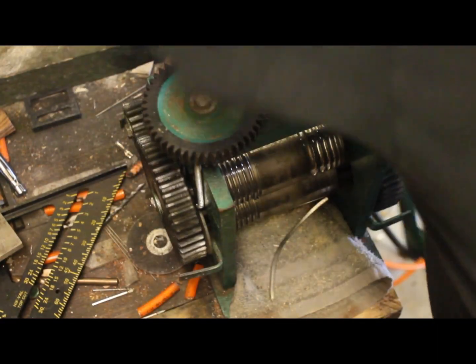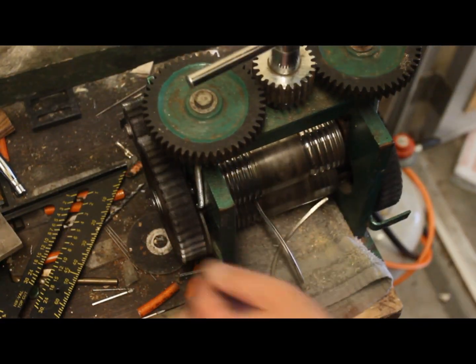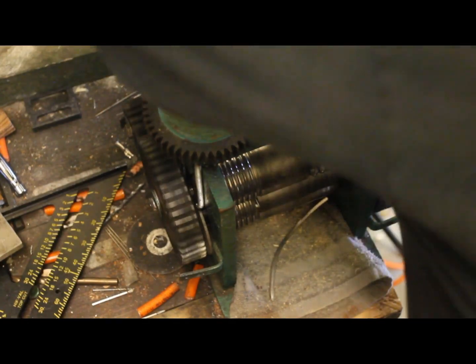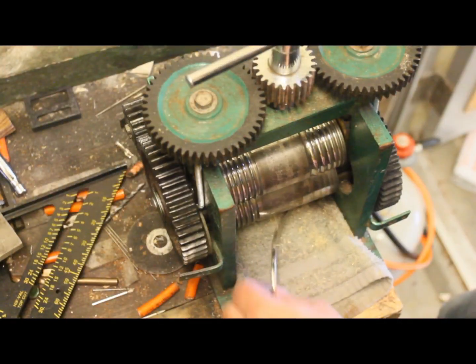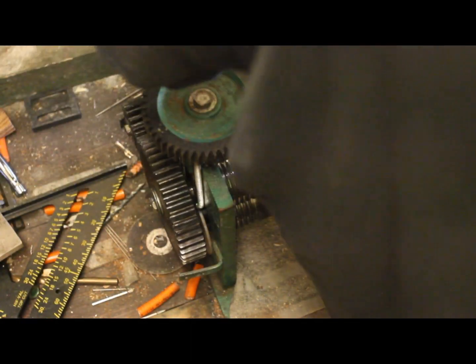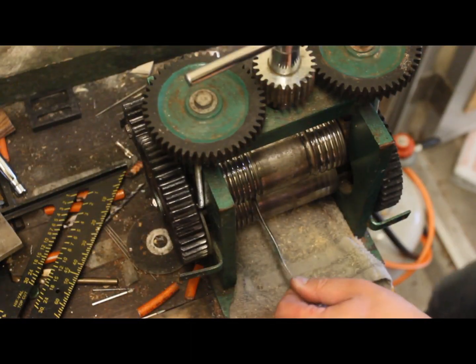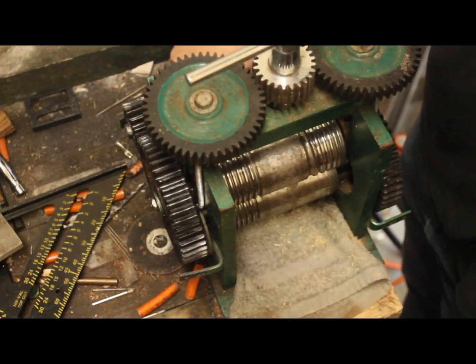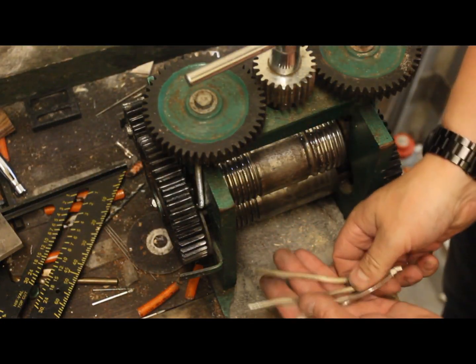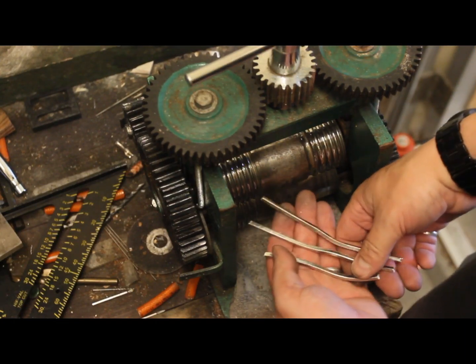We're coming up on the end of the biggest size of square wire that this rolling mill makes, and right here toward the end you'll see that they all came out very nice and square. I didn't have any issues when I was looking at them. I didn't see any cracks as I was going through, so my cast was good and I wasn't crushing them too fast. And then after this we just go to the annealing process.